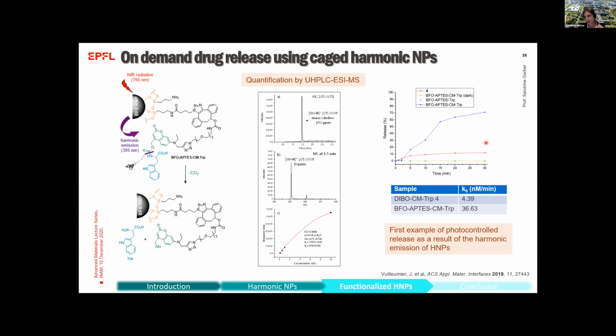And as you can see here, the cumulative release of tryptophan over time. Already after 15 minutes of excitation, you reach more than 60% release of the molecular cargo, and after 30 minutes you are between 70 and 80% release.